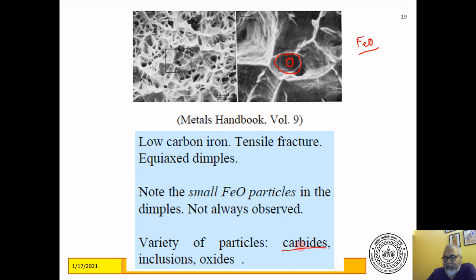Carbides are added. Cementite is a common constituent of steel. It can be inclusions like manganese sulfide. Manganese is added. Oxides like FeO that you see here, and all these dimples, therefore we know, are results of decohesion from these second phase particles. So the iron decoheses from the second phase particles and leads to these voids, which finally lead to failure.